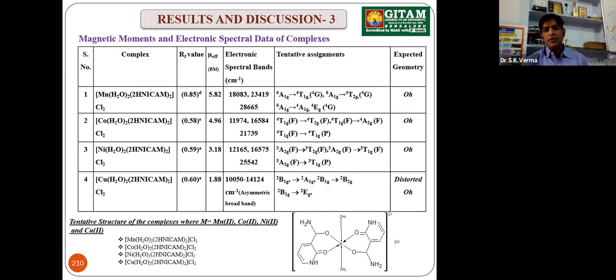Previous slide. Yes, the expected geometries are octahedral in the case of Mn, Co and Ni, and in the case of copper, the complex has distorted octahedral geometry, which we concluded on the basis of the asymmetric broad band that we found in the electronic spectra. The tentative geometry is also shown here, where the ligand uses both the oxygen atoms as donor atoms. Next, please.